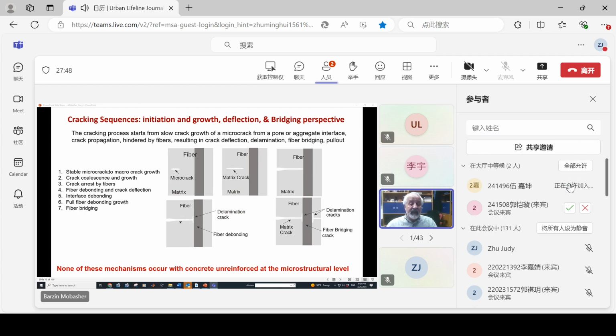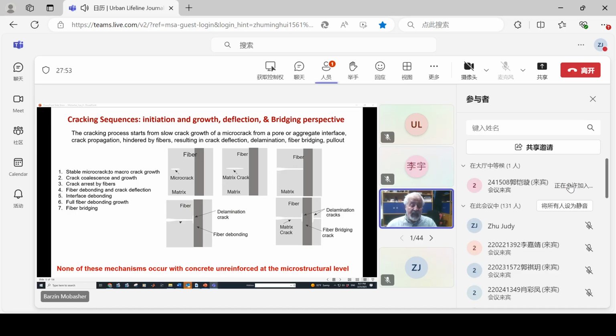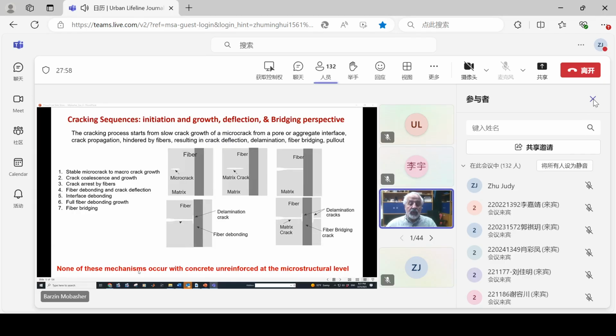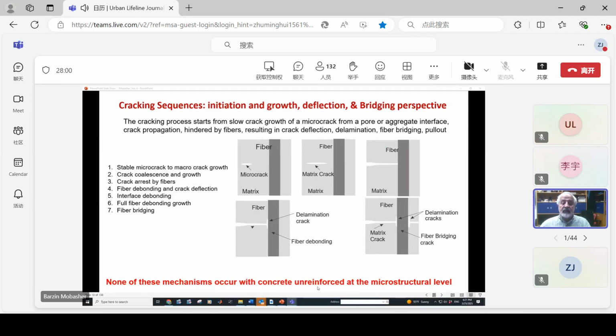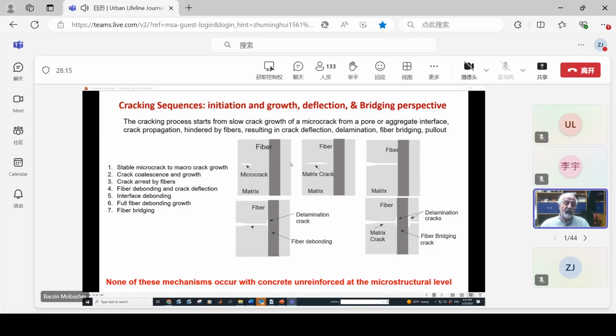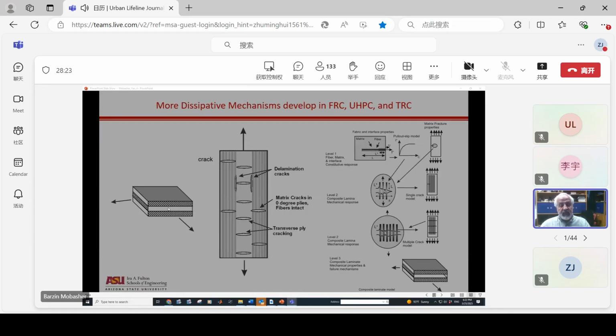This is good if you have fibers in there, if we look at the microstructure from a material science point of view. And I want to tell you one thing. None of these mechanisms occur with concrete if it's unreinforced at the microstructural level. Because for this initial microcrack to propagate, if there is no barrier along the path, all the energy is going to go through because the surface energy is so small for the growth of the crack. It's these nonlinear terms that generate and dissipate the energy that give us the added strength.